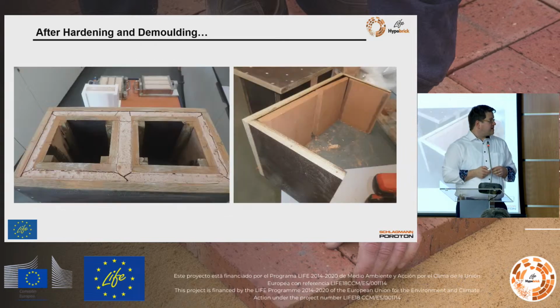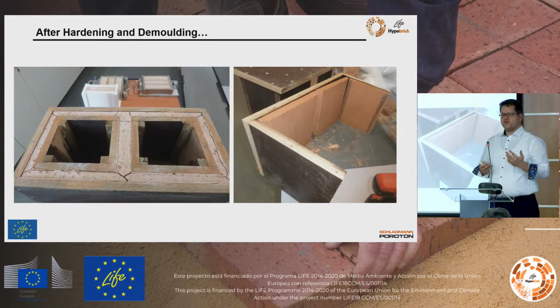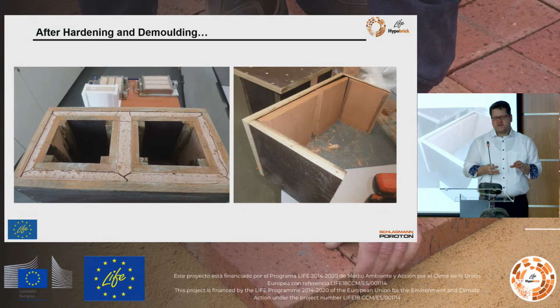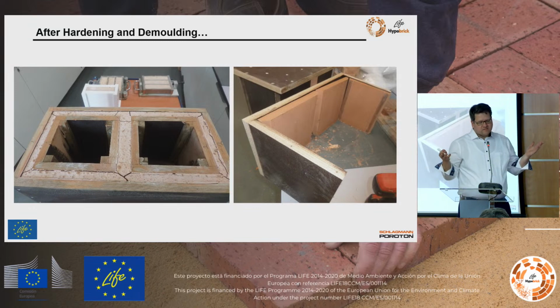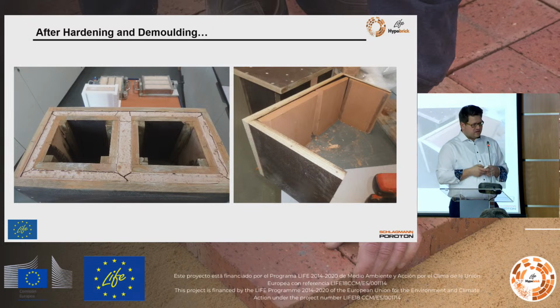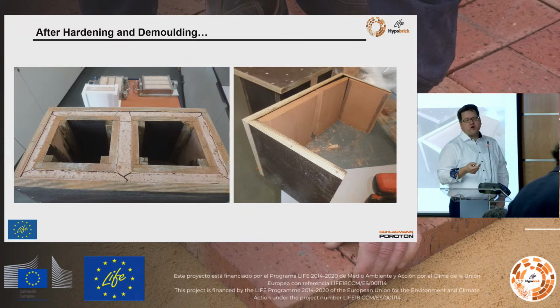Here the big challenge was the shrinkage. If we use this slurry with maybe too much water, it's clear that shrinkage occurs, like also for concrete slurries or whatever. But here you can see clearly in the picture that it caused cracks, especially at the joints of the cross and lengthwise webs, and therefore we have to overcome this problem.